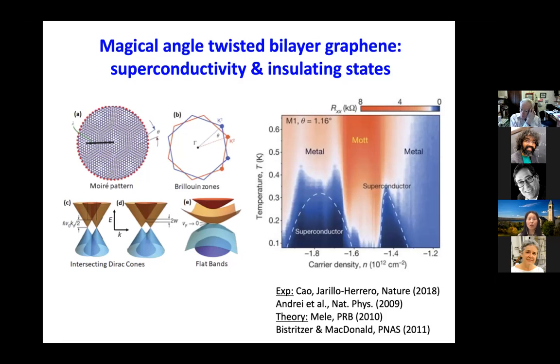hybridize. So if the hybridization energy between the two layers is comparable to the kinetic energy, that would change the dispersion of the band. And that happens at a magic angle, which is around 1 degree. So at that particular angle, because the two energy scales become comparable, the linear dispersion now becomes very flat. And this is how we get small bandwidth. And that's the case when interaction becomes important and the correlation comes in.